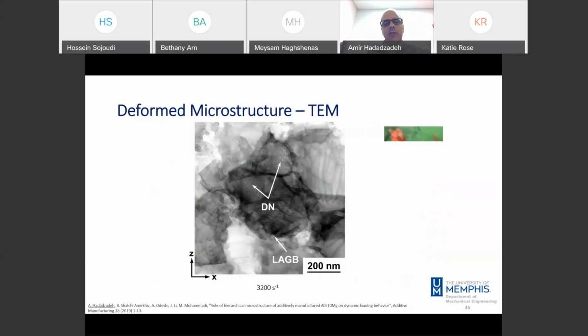Now for the second hardening regime, again, we have generation of new dislocations at high strain rate. After evolution of low angle grain boundaries, we have nanoscale grains. One of them is shown here, and they're bounded by low angle grain boundaries. Now the deformation will continue, and because of the deformation, we have evolution of new dislocations inside the grains. That's why we have the second hardening stage. So the hierarchical microstructure in SLM affected both quasi-static and dynamic loading behavior of the material.